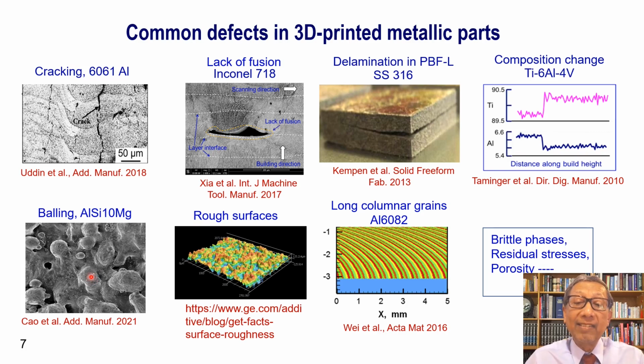There can be balling on the surface, or the surface can be simply very rough. And also during solidification, we can form long columnar grains that are detrimental to mechanical properties. The microstructure may have brittle phases, or the microstructure may have porosity. So all of these defects have to be mitigated while a new part is being developed. And because the cost of the machine and the cost of the feedstock are pretty high, we cannot do trial and error testing that we can do with conventional manufacturing. So models provide a very good solution because they are based on scientific principles and they require a minimum amount of testing. So I'm going to give you two examples of models to avoid distortion and surface roughness.